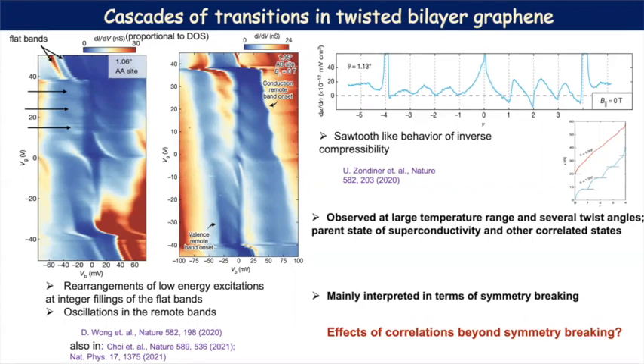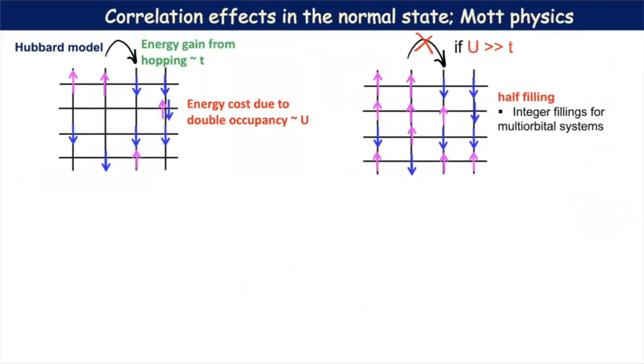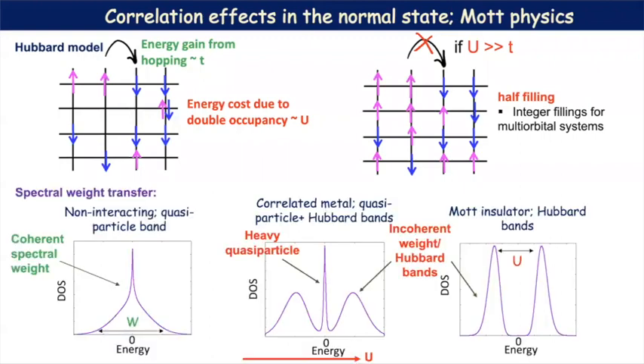So we already have some idea of how the Hubbard model explains correlation, explains some changes in the normal state through this Mott physics. This is associated to a spectral weight transfer. On the left, I have this coherent quasiparticle peak. I'm in the non-interacting limit, so this has some bandwidth. And then as I'm cranking up the value of U, you can see that the spectral weight from the quasiparticle peak is transferred to this incoherent Hubbard band. And we have a Mott insulator.